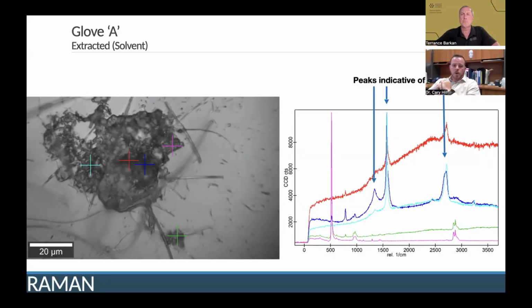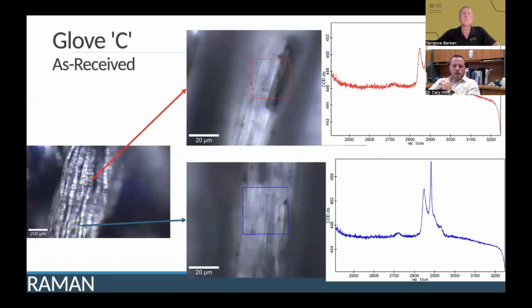Graphene would have a more single, less spread, less broadened peak. So we did not find evidence. This is not compositional evidence of graphene. It's more compositional evidence of graphite. And then I believe in some of the next slides, I'll have images of some of the particles themselves, where we did find thick flakes of graphite as well, for morphological evidence.